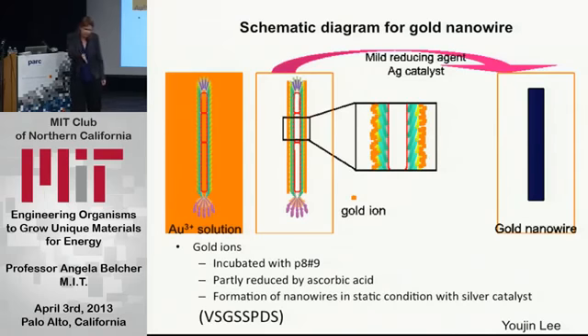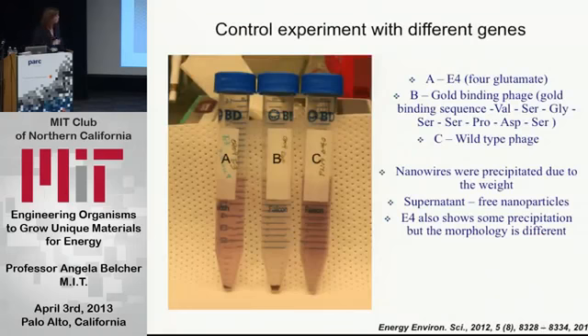And so it's very, very good at making these very nicely controlled wires. You can control the length, you control the diameter, and this is just 3 little tubes with different clones in them that we tested from our library.